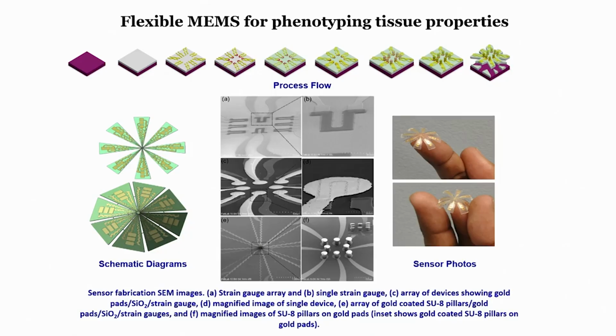Welcome to this module. In the last module we saw how to fabricate a piezoresistive sensor on a flexible substrate, and that piezoresistive sensor was made out of a conducting polymer called PEDOT:PSS. In the slide, step 1 is taking an oxidized silicon substrate, step 2 is spin coating PDMS, step 3 is forming a pattern of chrome and gold, and step 4 is forming the piezoresistor. These are an array of 8 piezoresistors. This is a single piezoresistor, an SEM image of that. Now we will see how we can form an array of gold pads on this piezoresistor.